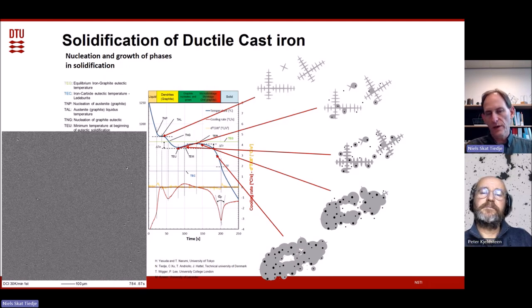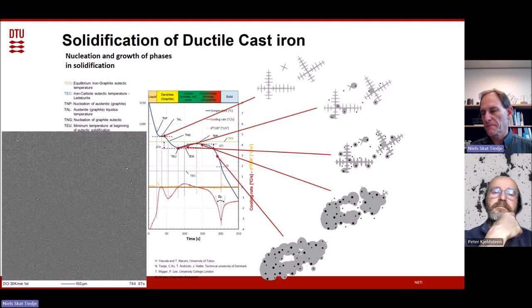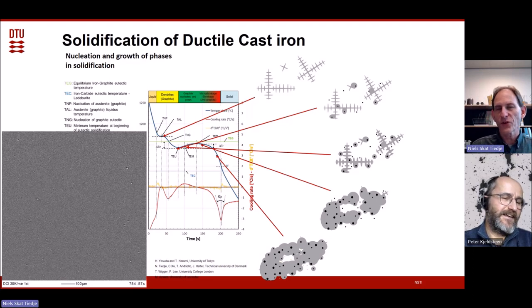If you're making thin wall castings, you use one type of inoculant because you have a high cooling rate. If you're doing heavy section castings, you have lower cooling rates, and you need to adapt to that. It's big business producing inoculants, because it's one of the most important parts of creating the microstructure that we need.